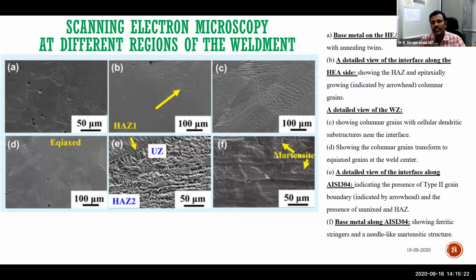So when we started characterizing that, on the steel side we started observing martensite. Okay, so martensite formation close to the fusion zone is normally very common in these systems. That's called recrystallized or resolidified martensite, due to the faster cooling rates associated with the system. And the cellular structure, which is observed in similar welding systems, here also cellular structure was observed. So this again evidences that we are supposed to get decent properties.